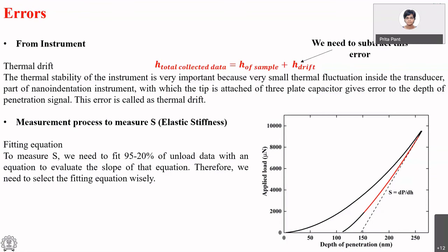Now, for experiments which are done over a short period of time, you don't have to worry about it because the instrument, or rather the software that runs your experiments, is set up to measure this drift before the experiment. So what it does is it has a very small load.